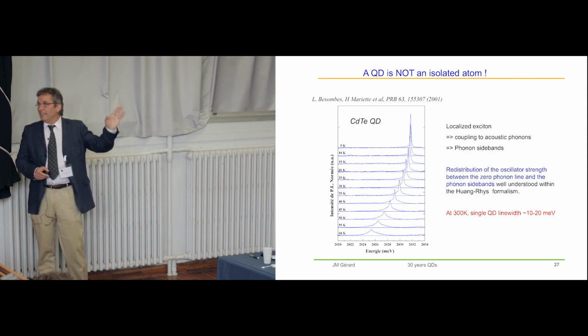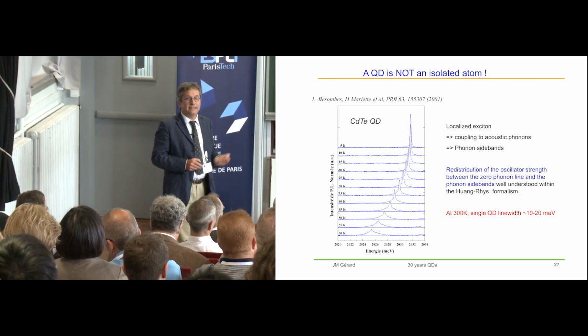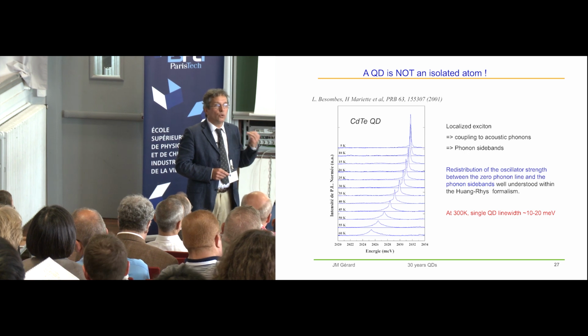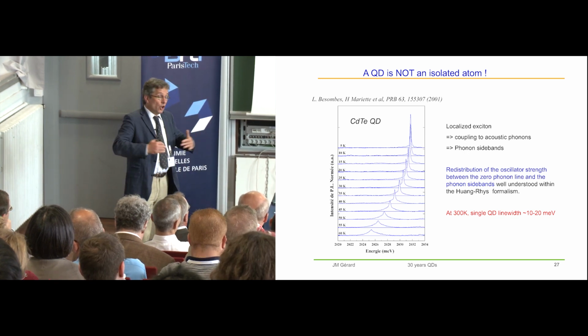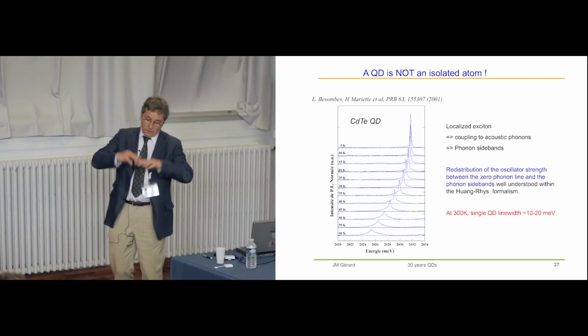In order to discuss that, the first thing I have to say is that a quantum dot is not an isolated atom. It displays very sharp emission lines at low temperature, but when we increase the temperature, we increase the population of phonons inside the phonon bath, and we see here that single quantum dots exhibit on the PL spectrum very broad phonon-related wings. At room temperature, the emission line width of a single dot is typically 20 meV. This tells us many things. First of all, we are very far from the original dream of Arakawa and Sakaki. We will never get, at room temperature, very sharp emission lines for ensembles of quantum dots.